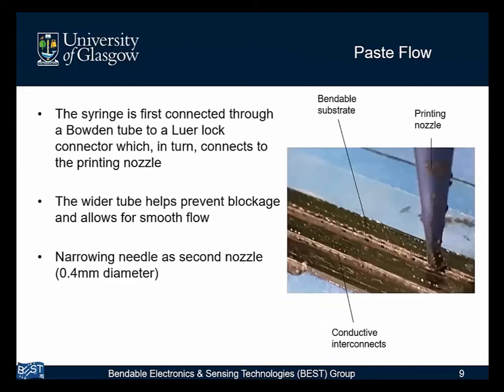The paste flow itself goes through the syringe and through a Bowden tube, and through that, through a Luer lock connector and through a nozzle. The particular nozzle we chose is 0.4 millimeters. However, another advantage of this is that the nozzle diameter is easily changed by changing the nozzle itself.